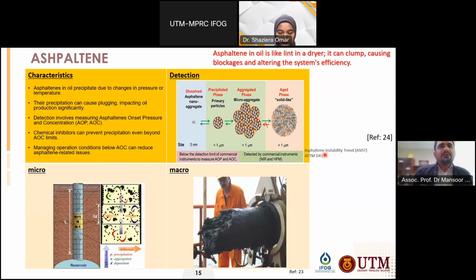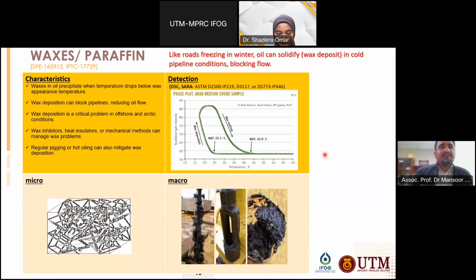Okay, so this is wax. The characteristics of wax are included here, and as you can see, wax in oil precipitates when temperature drops below the wax appearance temperature. So it can, of course, potentially plug the pipeline and reduce the oil flow rate. Wax deposition is a critical problem in offshore and Arctic conditions. Wax inhibitors, heat insulators, and mechanical methods can also be used to manage the wax problem. Normally we use pigging or hot oiling in order to mitigate this wax. There is a case study, and I'm going to present it for you about this.